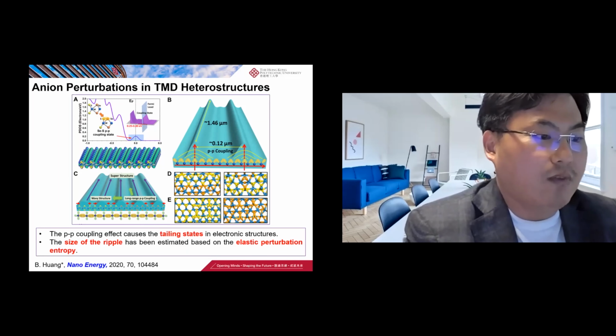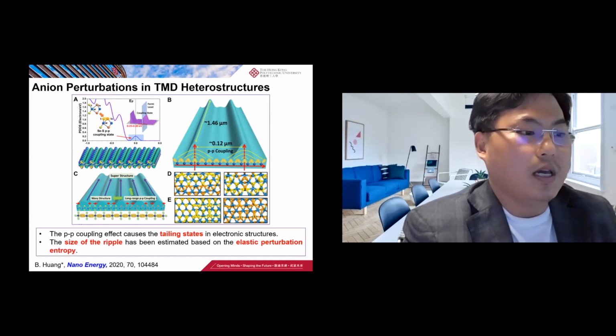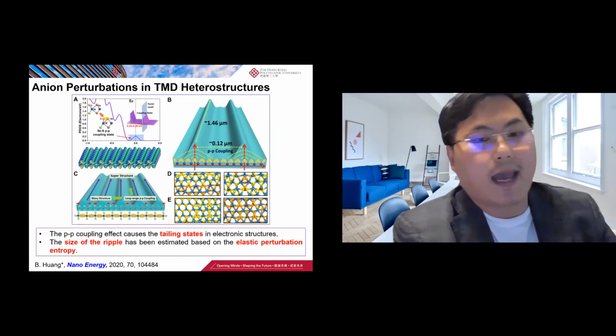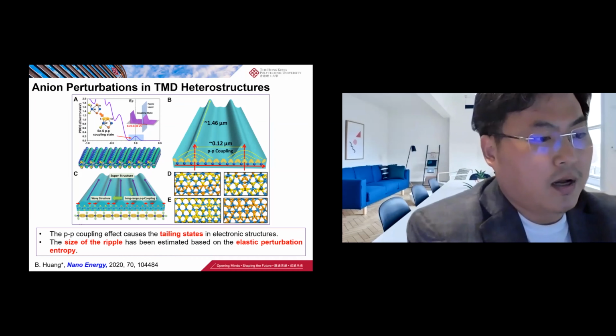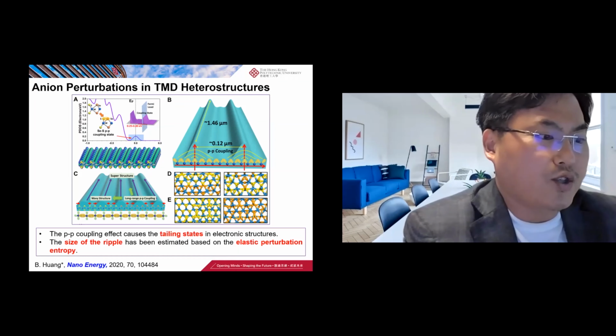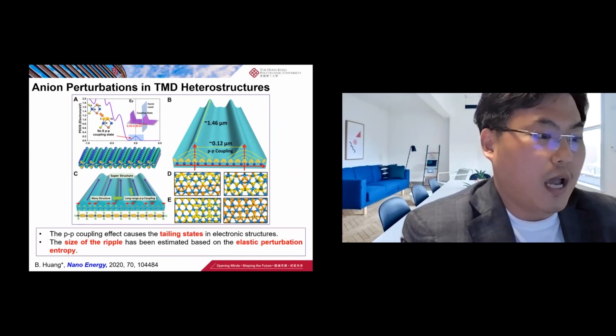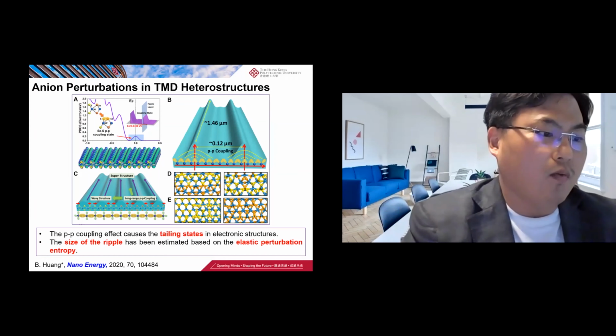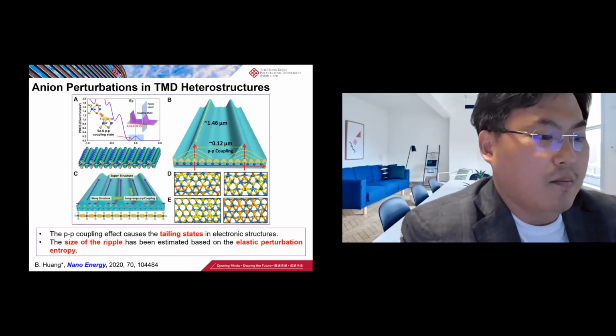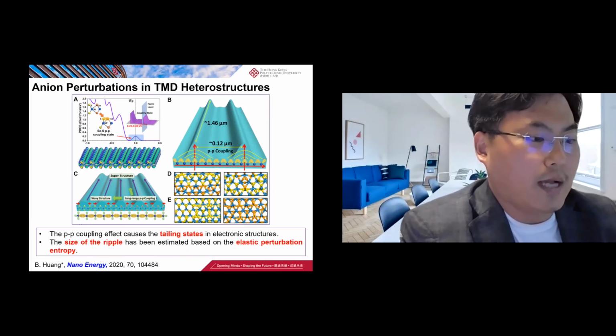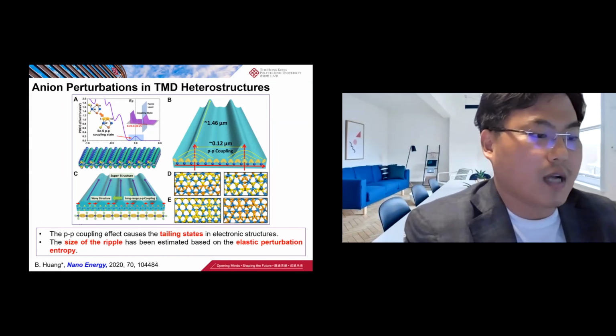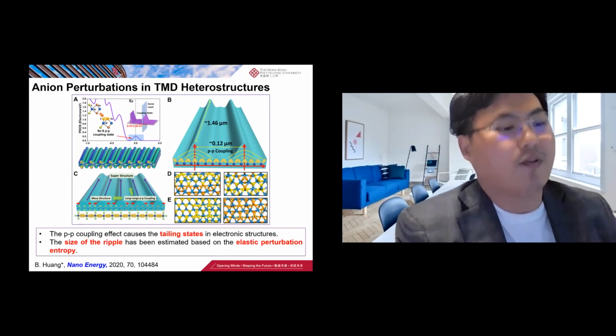So this confirms that the electronic structures are also an essential factor in modulating the mechanical effects of the in-plane phenomena. Through zooming in on the structures, we are able to observe the structural evolutions of the lattice structures from the original superstructures. Based on our works, we have proposed the elastic perturbation entropies, which are able to quantify the ripple size of the ripple structures based on different structures.